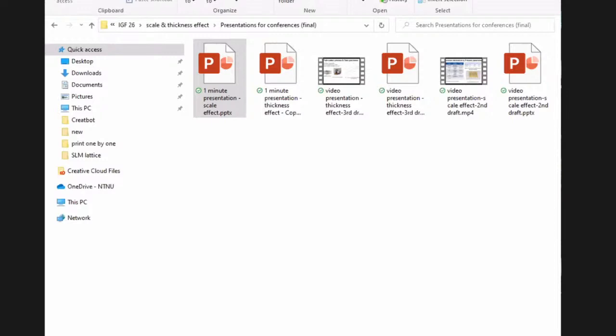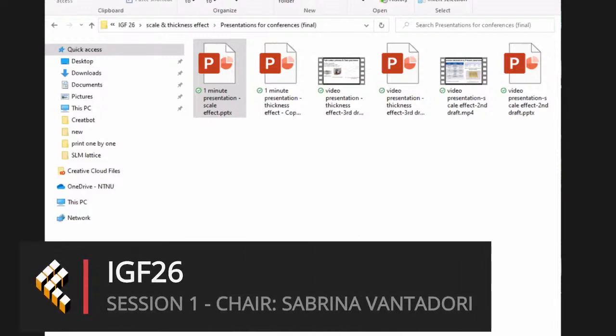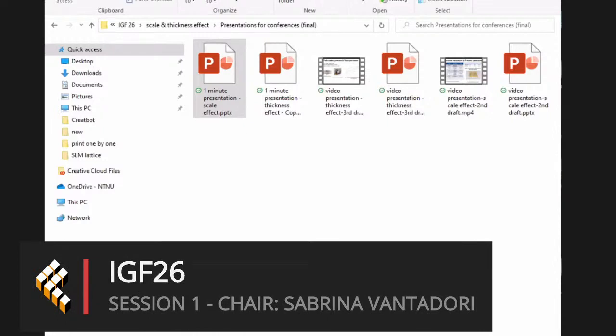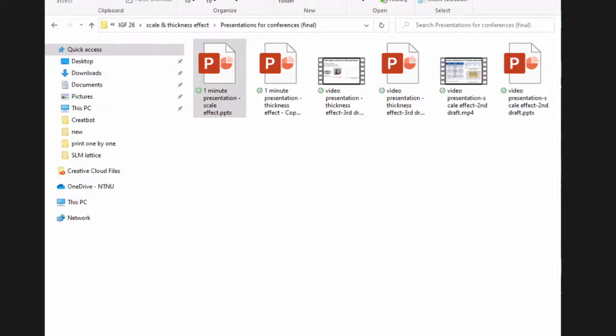The reason could be, first, the first layer quality. As you know, for FDM printing, the first layer quality is very crucial for the specimen, and sometimes it may vary. And also, it's because of the possible weak spot near the edge of the gauge length. Because for this printing process, I observed that every time when each layer starts printing, it didn't start at the edge of the specimen. Instead, it starts somewhere near the gauge length, as I showed in the video before, so that might be the possible reason.